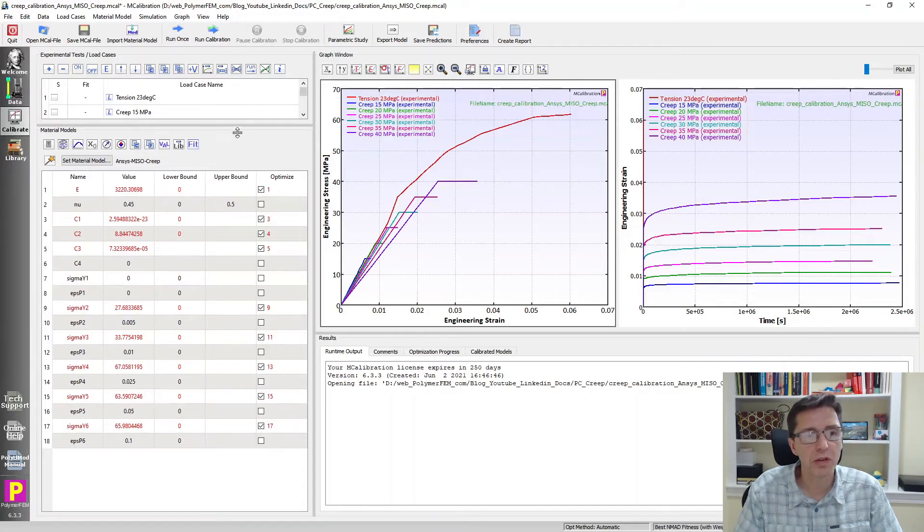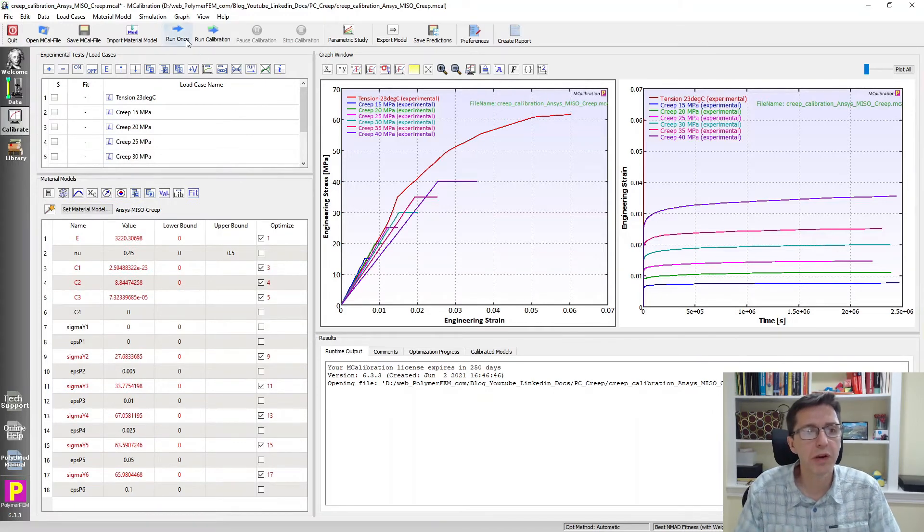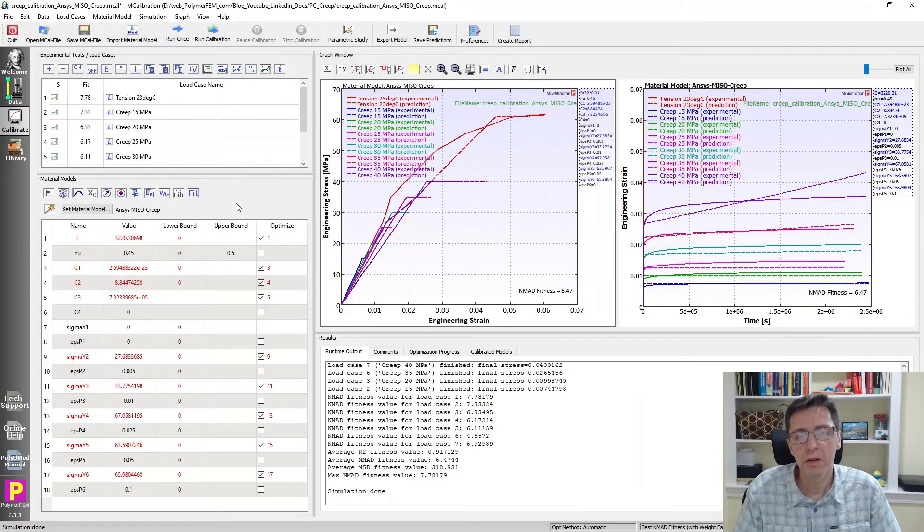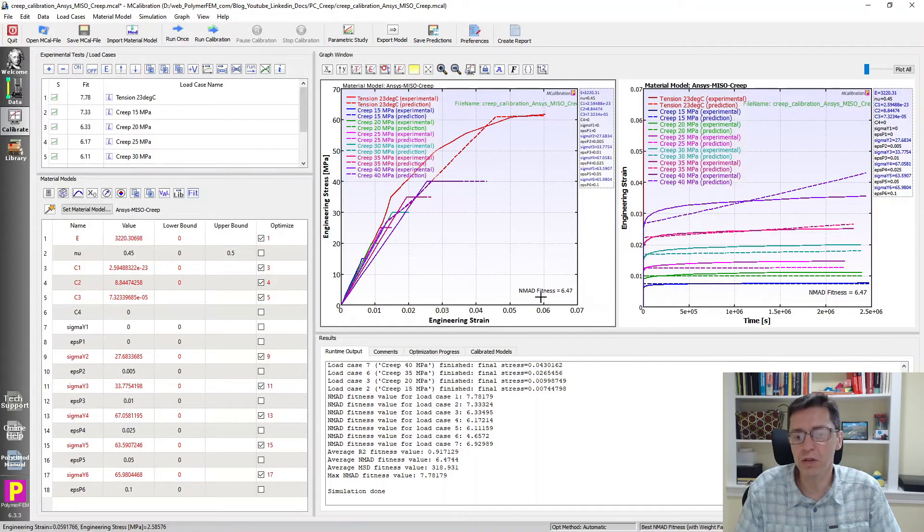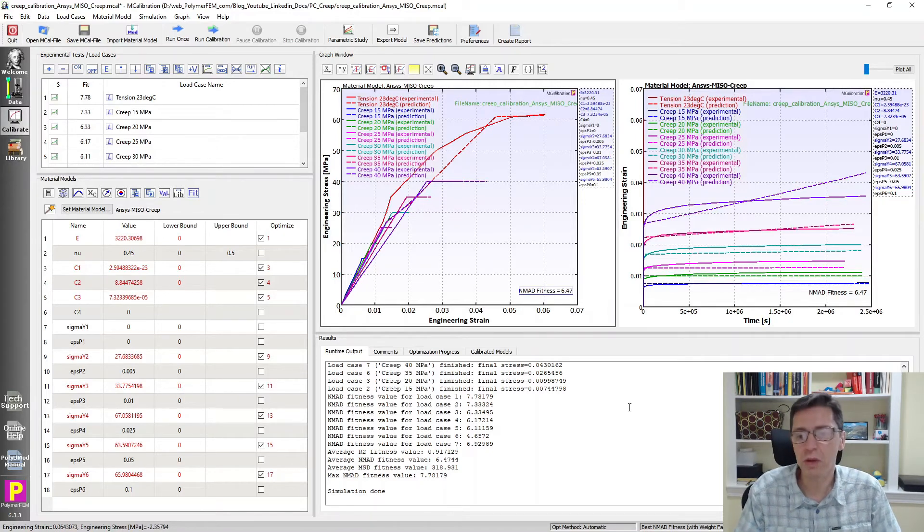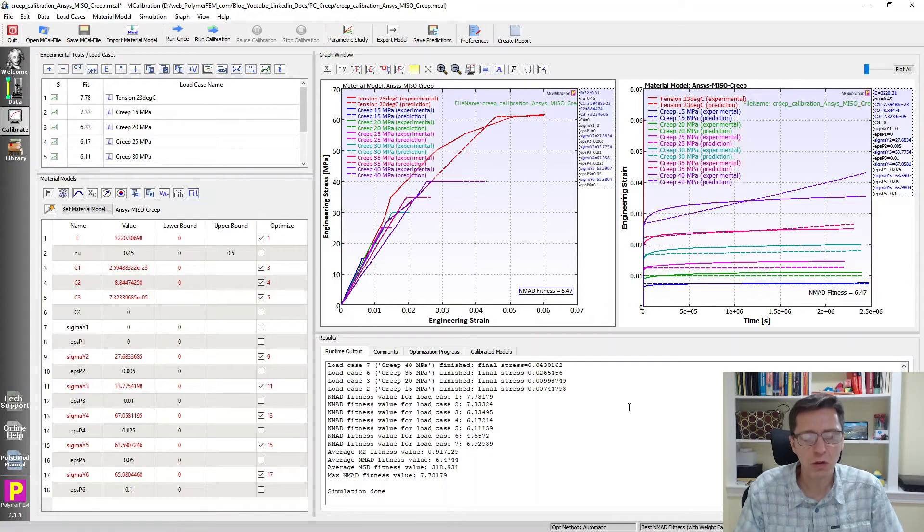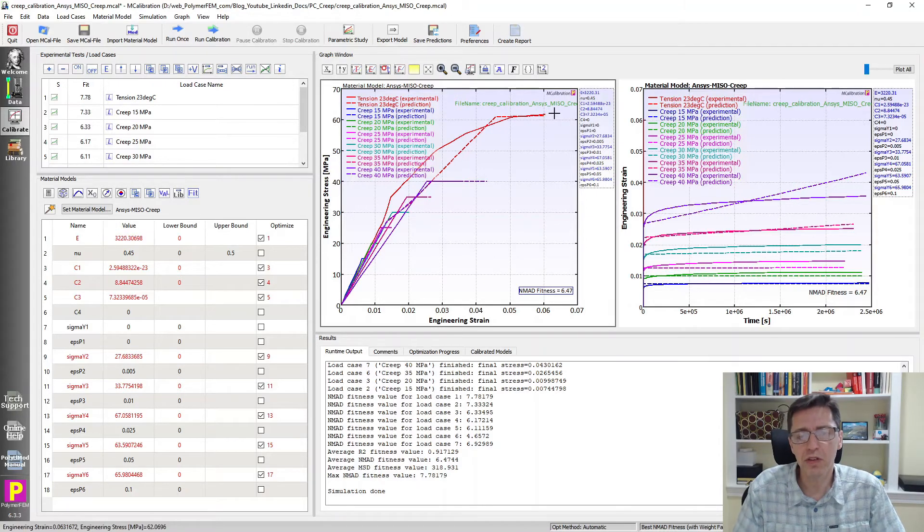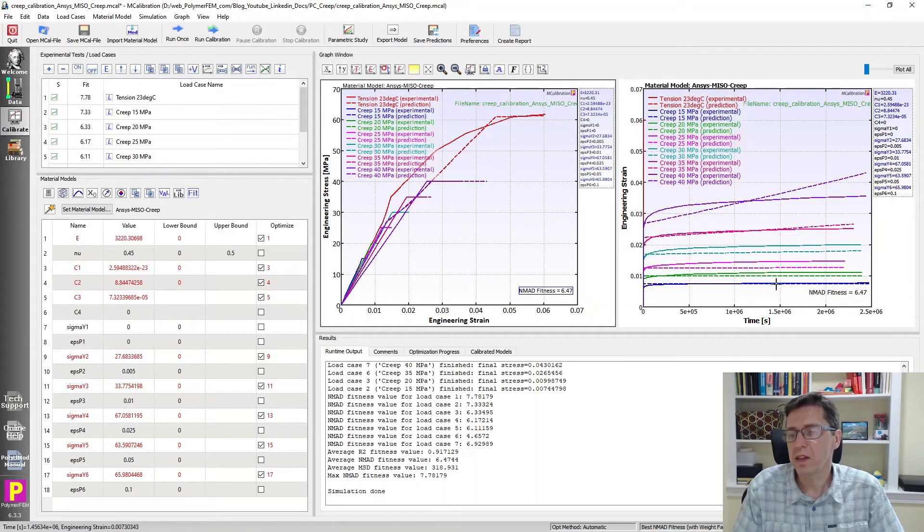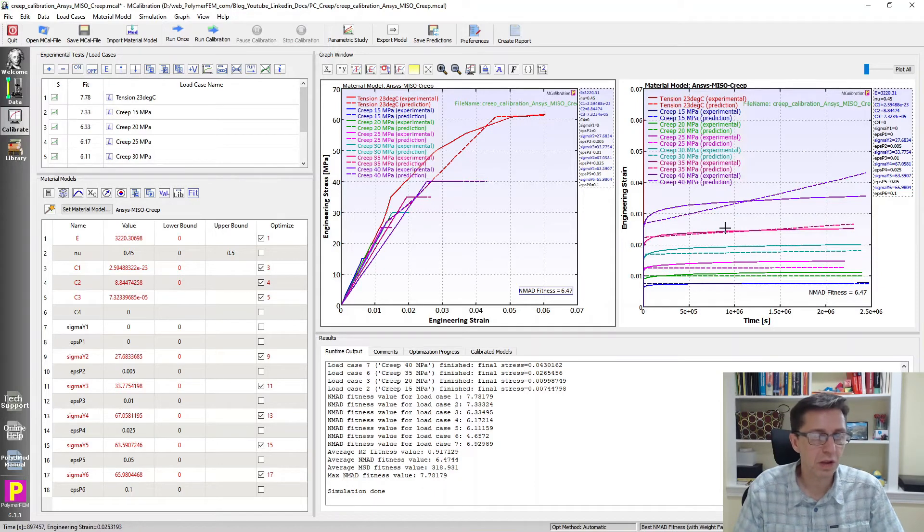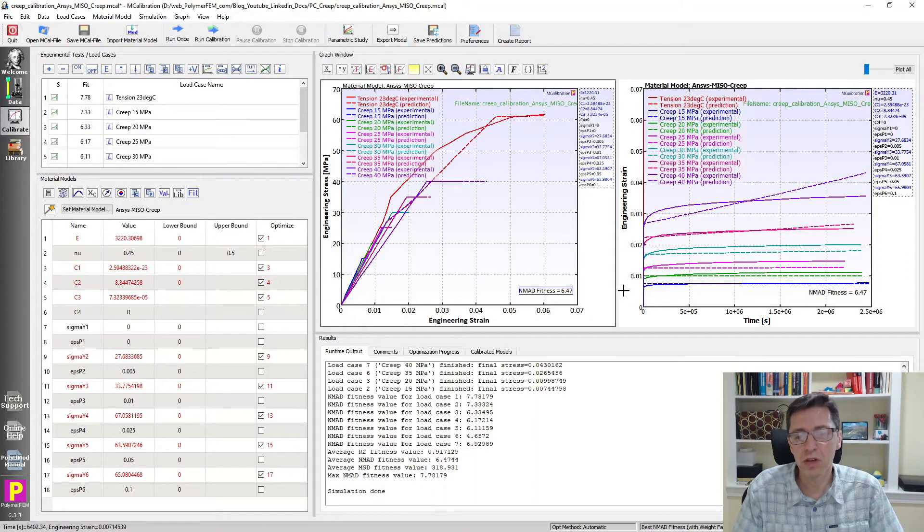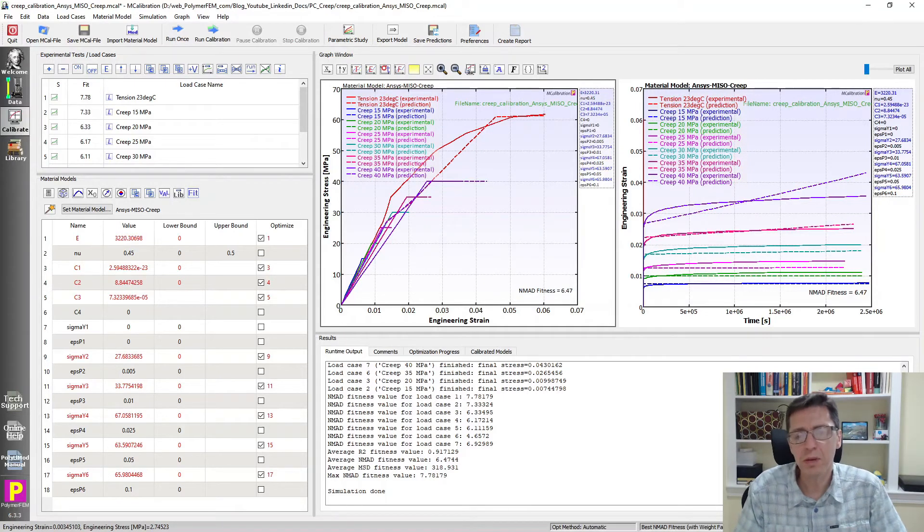Then I can just calibrate it. The easy part here is this calibration. Once you select the material model, you can quickly calibrate it. And if I run this one, we'll see that now the curve starts to roll over due to the plasticity. That's nice, of course. We get an average error of approximately 6.5%, which is not too bad. It matches the overall trends of this data set relatively well. It also predicts the creep response pretty well. The change in slope of the creep curves increases with the creep stress. This is surprisingly good for this data set.